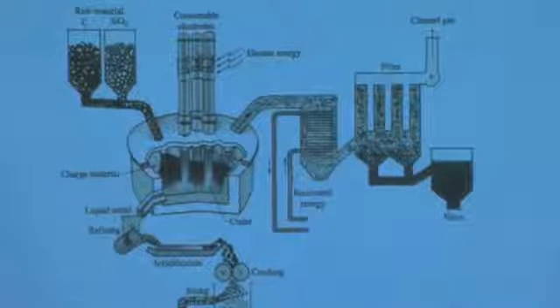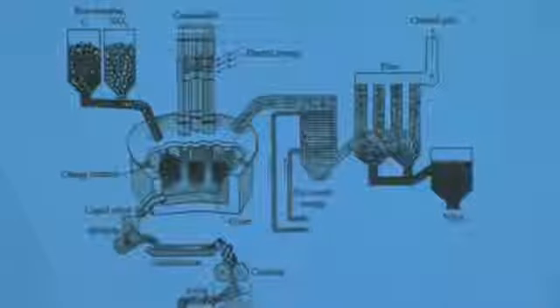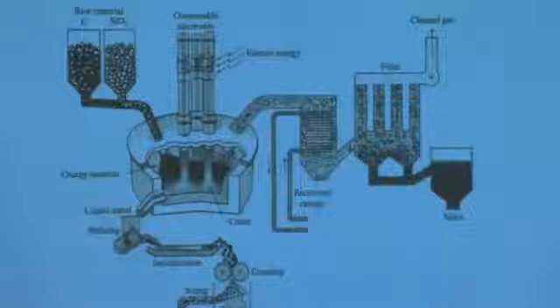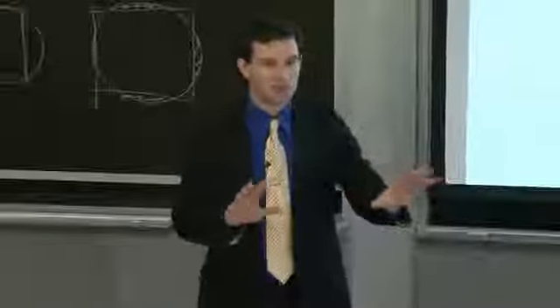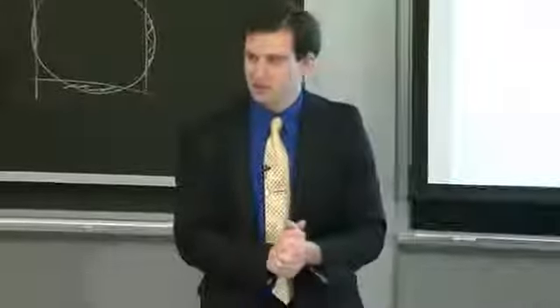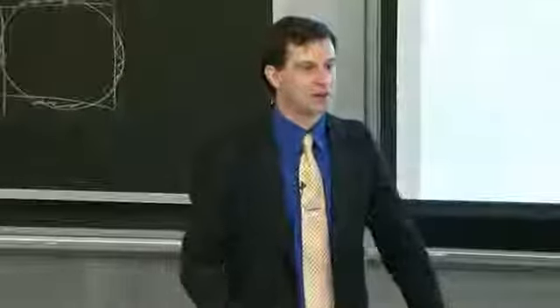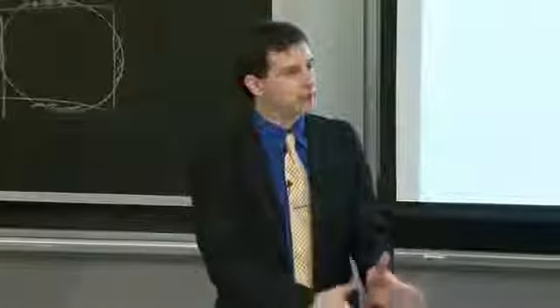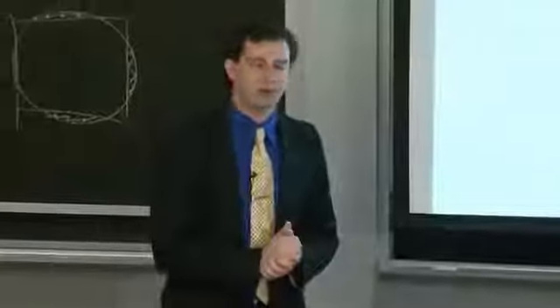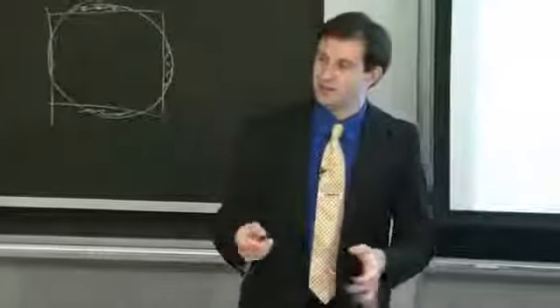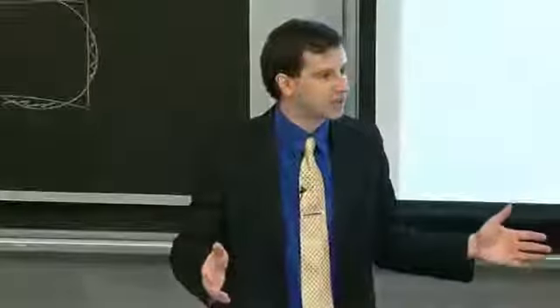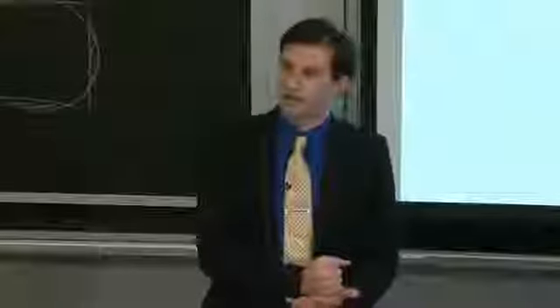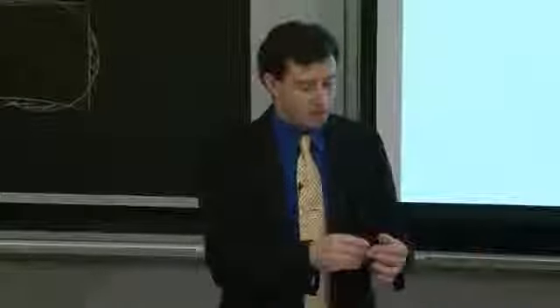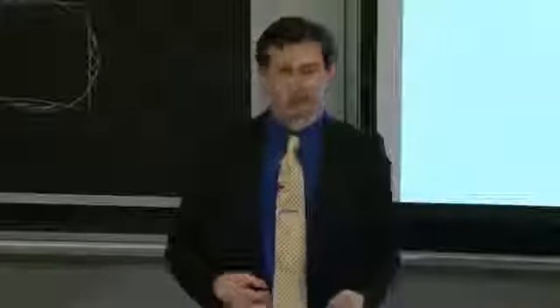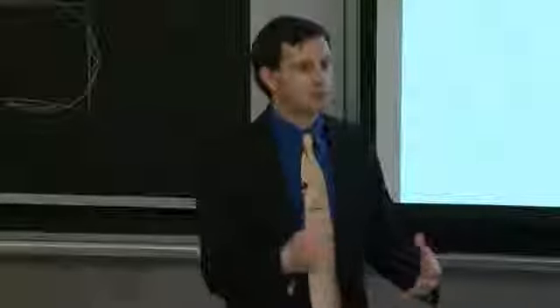That can be some high purity pegmatite. It could be, for example, a hydrothermal quartz, higher purity varieties of quartz. You could even use maybe a metamorphic quartzite material. Let me explain. So some of the highest purity materials are coming from these veins of magma that flowed up and then phase separated during millennia. Some of the lowest purity quartz is coming from sand, essentially crushed rock that made its way into, say, a beach-like environment. And then rock was deposited on top of that, pressure was increased, and this whole mixture of mica, feldspar, and of quartz got pushed together and formed a solid block.